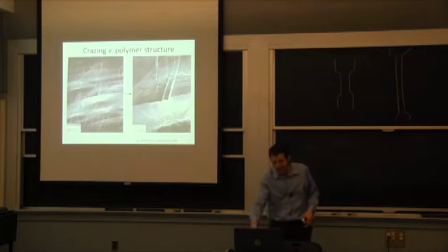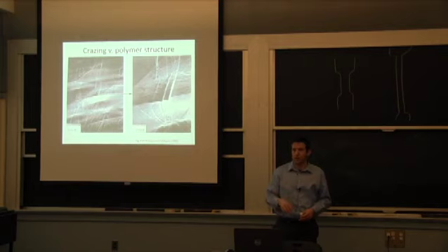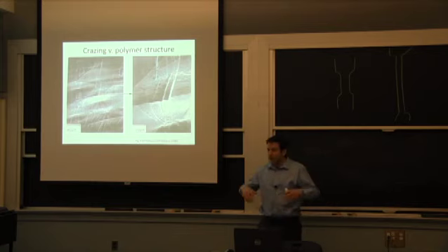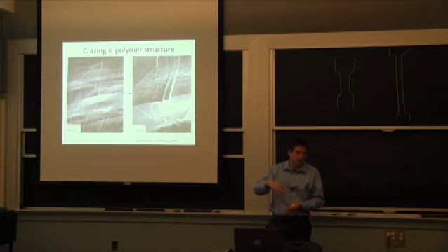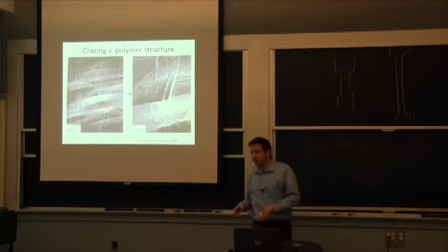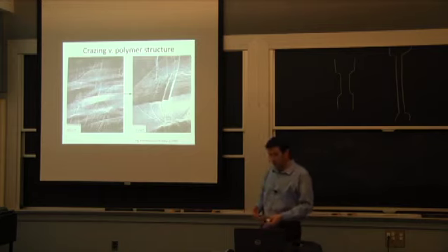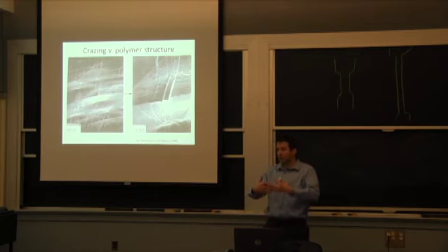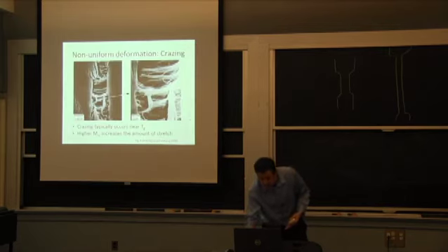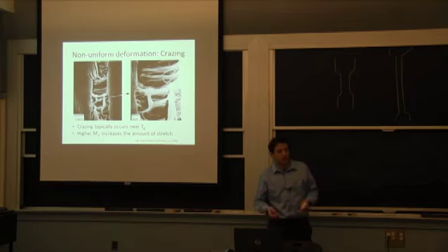These are more or less spherulites that you can see on a cut section, a little hexagonal equivalent shape. So you're trying to stretch these spherulites, but right on the nucleus, you have a lot of triaxiality, you have a lot of tension, and you can start forming voids. Now, it will be different than in the middle because you start forming voids. That happens, but those macromolecules still don't want to separate around it. So you form these fibrils that you see right here, and some people call it stress whitening. So if you take a piece of plastic that's relatively rigid, you can see that happening.